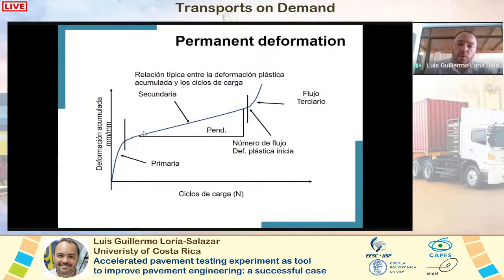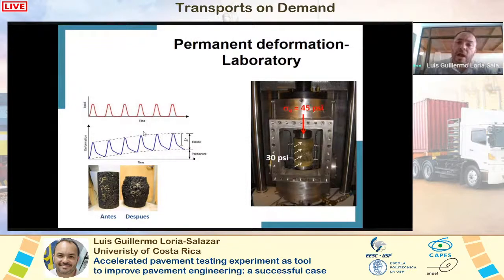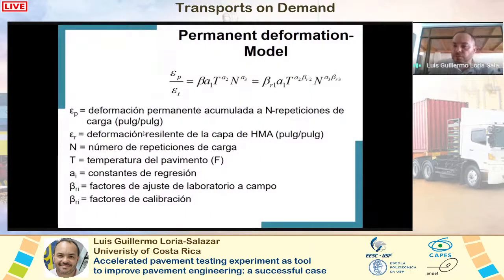I'm going to show you the models developed for permanent deformation. For our HMA material, we do the laboratory analysis using the typical triaxial test, the repeated load triaxial one. And we try to match the permanent deformation at the lab stage with the HVS stage. We use a shift factor to calibrate models, having the lab testing and, of course, the field testing, because it's very important.